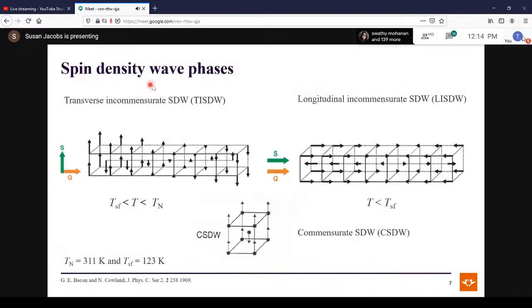Okay, so we keep saying spin density wave. What is it actually? It is just the modulation of the local spin density vector. So it is an antiferromagnet. We have the moments at the corner of the lattice parallel to each other, but anti-parallel to the moments at the center of the crystal. In a regular antiferromagnet, you would have the moment magnitudes equal throughout the lattice, whereas in the spin density wave case, you have a modulation of the magnitude of the moment. So you have a sinusoidal variation.